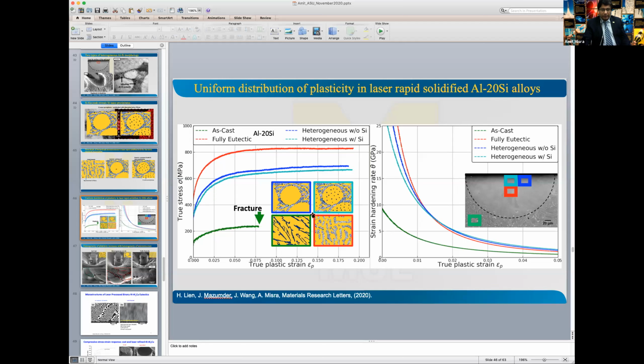And generally, my guess is it will not be very stable. If we take it up to 300, 400 degrees C, the structure will coarsen. But we need data to understand how rapidly, and we need ways to make it more stable, because right now the applications will be at room temperature, but if you want applications at elevated temperature for aluminum, there's a lot of promise, but we may have to find some other alloying elements to make it stable at elevated temperature. But I think it's opened up that kind of area.